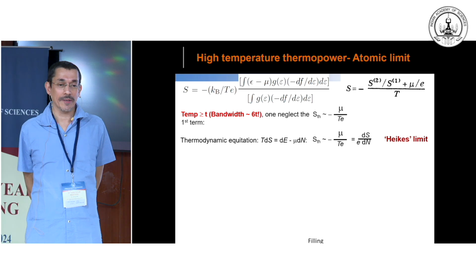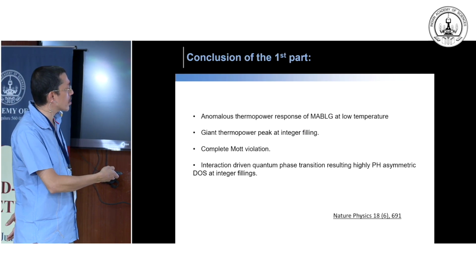Yes, that's true. Yeah. So asymmetry is what you think will explain? So that's the way we say that asymmetry of the density of state, the flat band, is very crucial. Then it's the effective mass which is probably dominating the Seebeck. That's like a large density of state you are talking about, because effective mass eventually will give a large density of state, inversely proportional to its density of state. So, in fact, when you have a flat band, it's in a very tiny region of the K space. Right. So effectively the number of carriers is not very large, right?